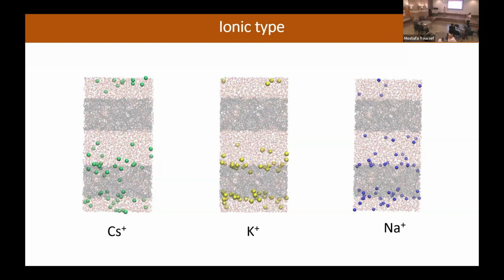From other works on carbide-derived carbons, CDCs, the work of Mathieu Salanne and Benjamin Rotenberg in Paris, they were showing that the pore distribution is shifted towards larger pores. And in those pores, they do see pairs of plus and minus ions together, which we don't see in pores that are less than 1 nanometer. In Romain's simulation, when the ions get into the pore, they are basically naked. So that's very different. You found a very different behavior. Yeah, that's one thing we have to try as well: the pore size, the chemistry. Great stuff. Okay. Thank you.